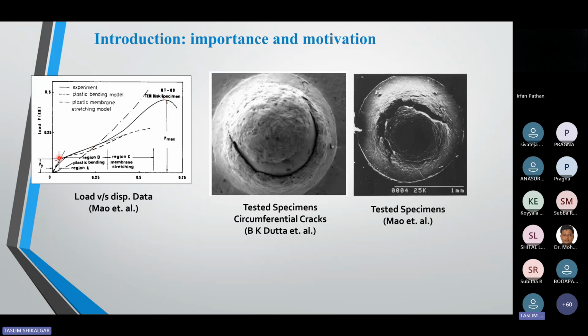They generated correlations of yield stress versus yield load, as well as ultimate tensile stress versus UTS load. These types of correlations are available for many materials. They developed a database for many materials, and based on that database, they generated correlations. With the help of these correlations, you can find mechanical properties using these specimens. And if you get any new material, you need to make a new database, because you cannot use the old database for newly upcoming materials. That is another challenge with SPT.